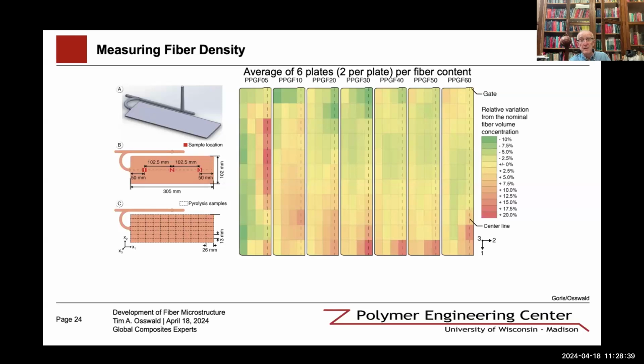There is a significant change in fiber density. You can see, at the typical filling fiber content of 20, 30, 40% that is used commercially, that there is a huge fiber density at the end of the part. And that's very typical. So if you have a part that you mold, the last place to fill usually has the highest fiber density,